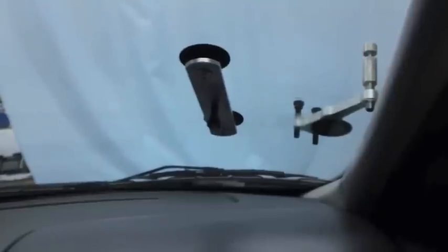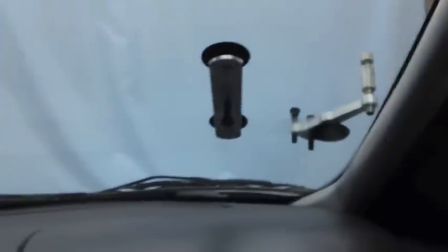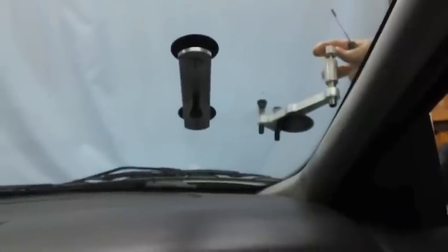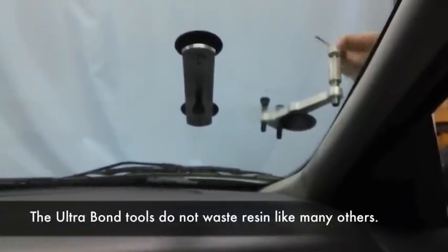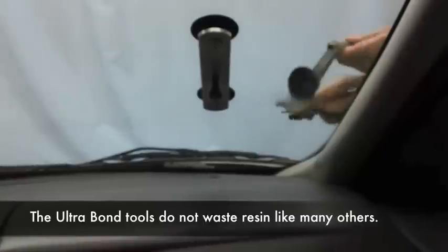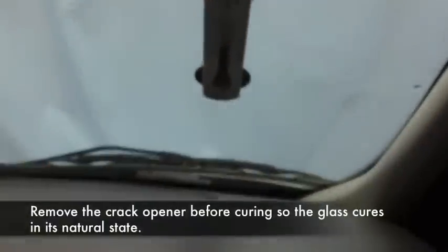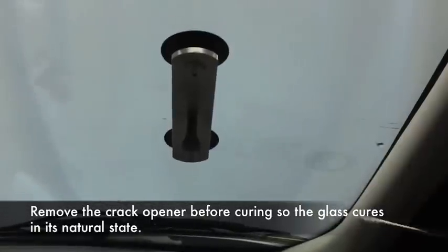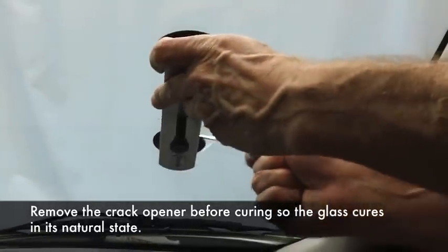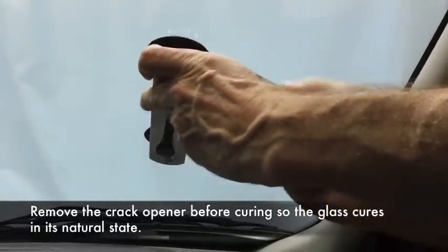Slide off the crack with a quarter-half turn of your injector so the resin doesn't spill on the windshield. Loosen your crack opener. Never cure with your crack opener on, because the resin will cure and then you'll take the crack opener off, and because the glass wasn't in its neutral position, you will end up refracting the resin.